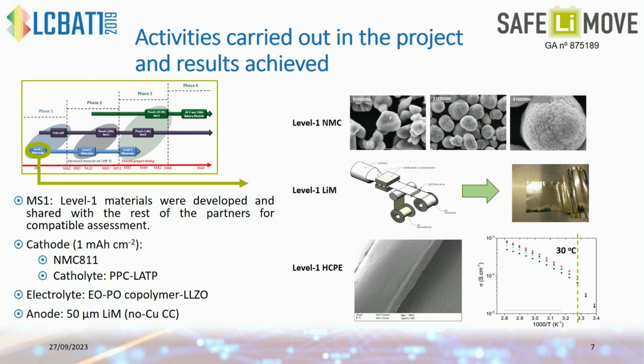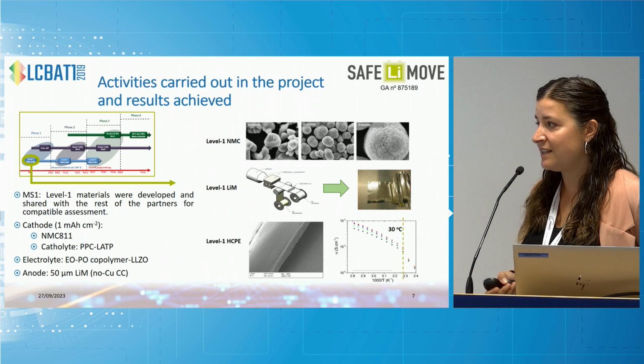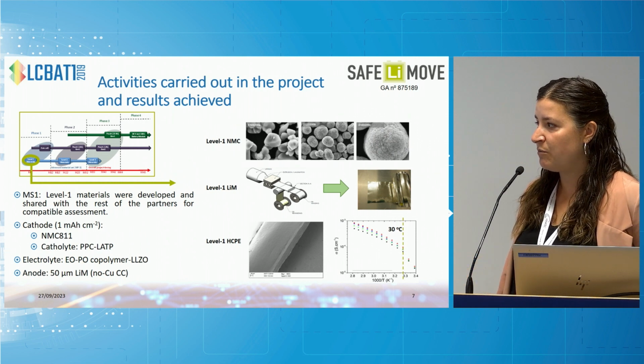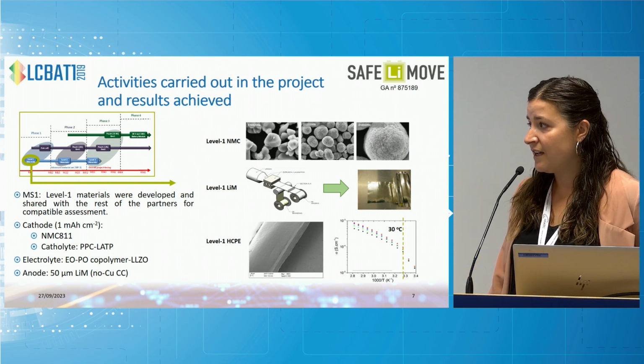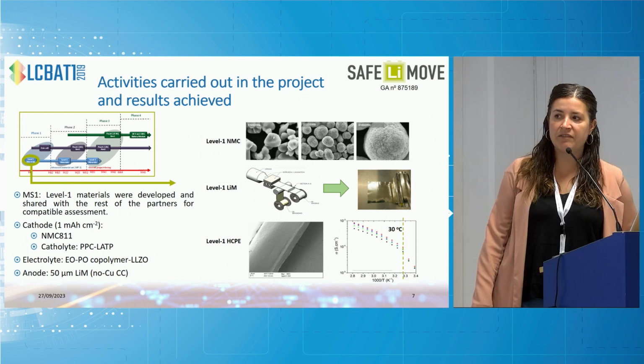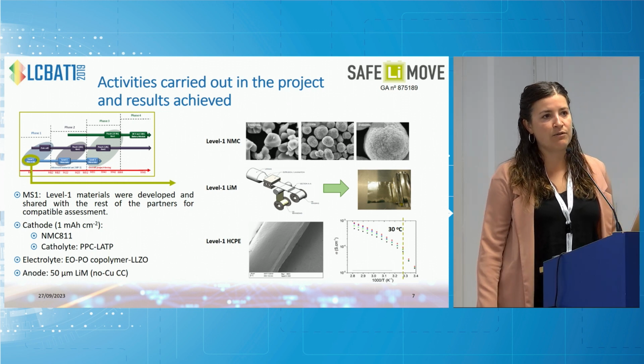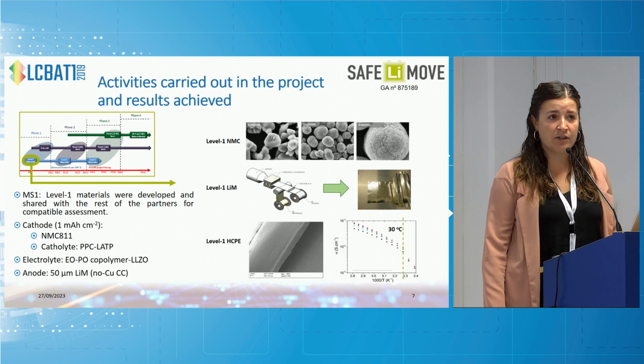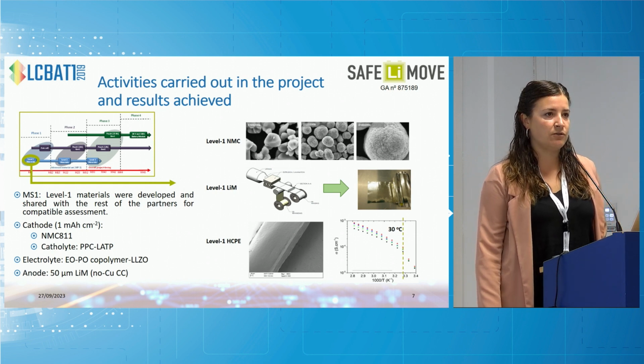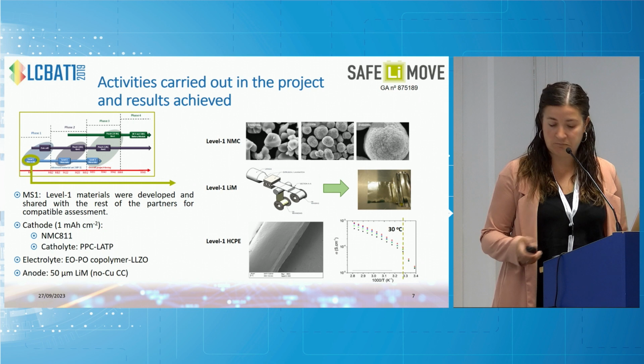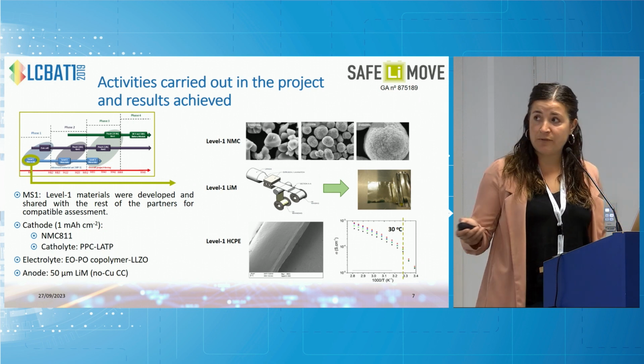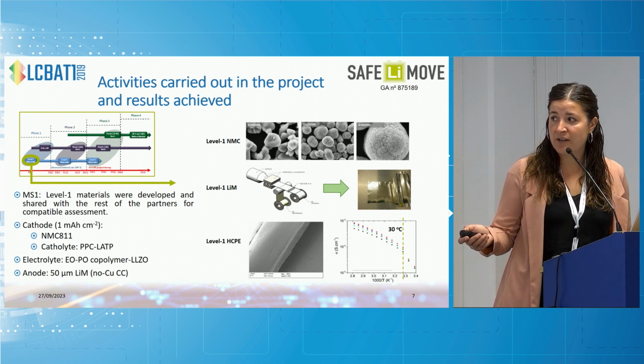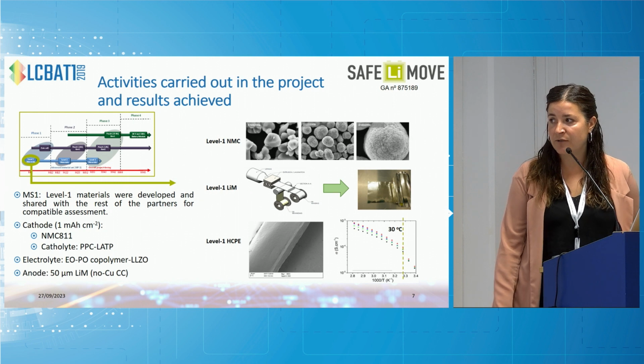Then for the electrolyte, we were looking for a polymer chemistry that is more compatible with the lithium metal interface, that is based on ether containing polymers combined with garnet. And for the anode, we had a 50 micrometer lithium metal, self-standing without the use of a copper current collector, which for sure has an impact on the final cost and the energy density. So the assessment of these materials by means of the electrolyte, we were able to have ionic conductivities close to the target of 10 to minus 4 at a room temperature.